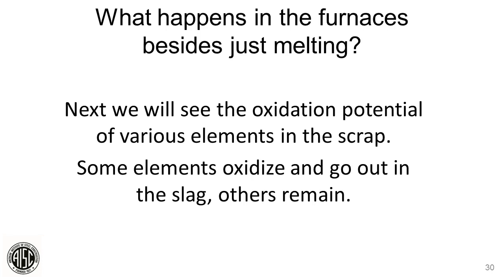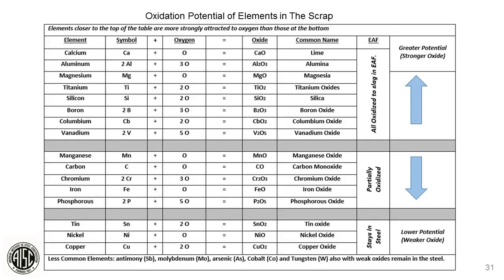So what happens in the furnace besides just melting? We're going to talk about some of the oxidation potential of various elements in the scrap. Some of the elements are oxidized and go out in the slag, others remain. But basically what we're saying here, when you think about the electric arc furnace, that's an oxidizing process. When you go to the ladle metallurgical furnace, it's a deoxidizing process. So the high temperature thermochemistry reactions there are two completely different processes and different routes of what we're trying to accomplish. So as we go to the next slide, we'll go through that in a little more detail.